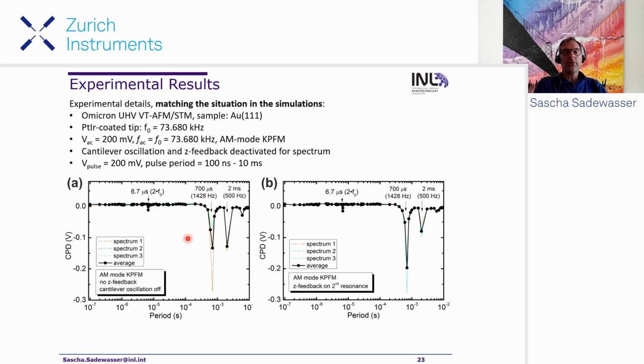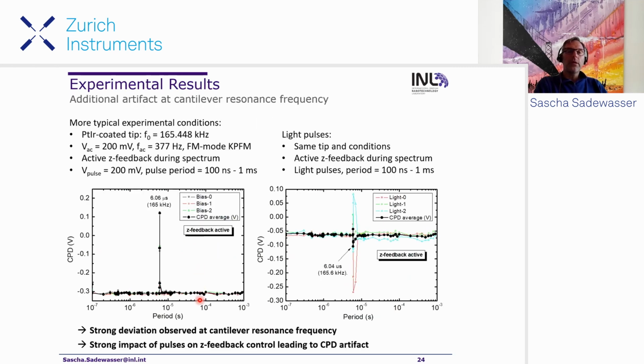These two spikes here are due to capacitive effects that we ignored. Actually, what you get in many experiments is not that one, but you're much more sensitive to the resonance frequency of your cantilever when you do bias pulsing or light pulsing, because normally you keep the Z feedback switched on, and then you get some coupling between the cantilever oscillation due to either the bias or the light pulses. So even the light pulse can reflect into the photodiode. So this normally screws up your Z feedback, and you get a much higher peak at this resonance frequency that screws up your Z feedback essentially.